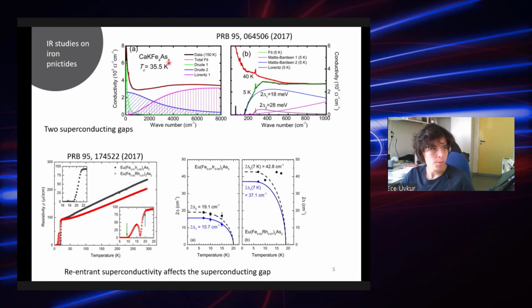Similar optical studies had already been done before we did it on the europium compound. It has been done for the calcium-potassium 1144 system, and it looked pretty much like any other iron pnictide system, with 2 Drude components and high energy transitions. When the system becomes superconducting, 2 superconducting gaps open. One interesting thing was that for this re-entrant superconducting material, there was some reduction in the superfluid density or the gap size when the europium orders. This was also one of the motivations for us to take more temperature points below the superconducting transition temperature, to see if a similar effect is also observed in the europium case.